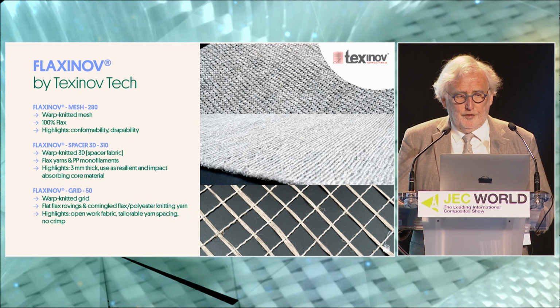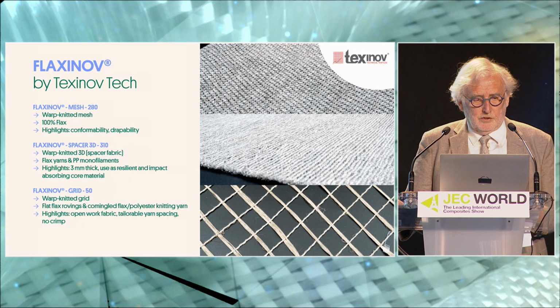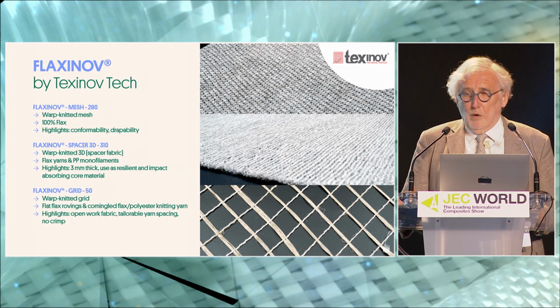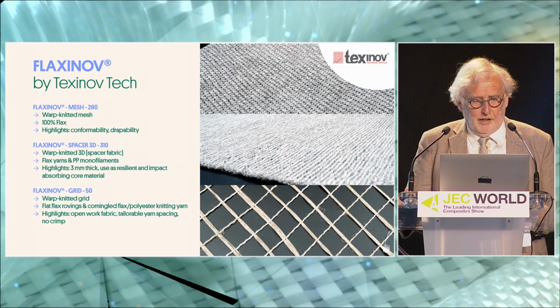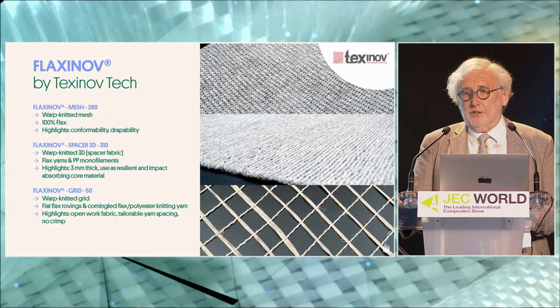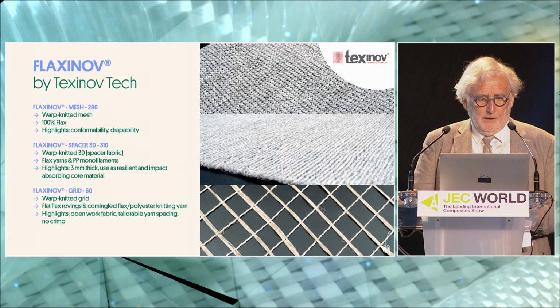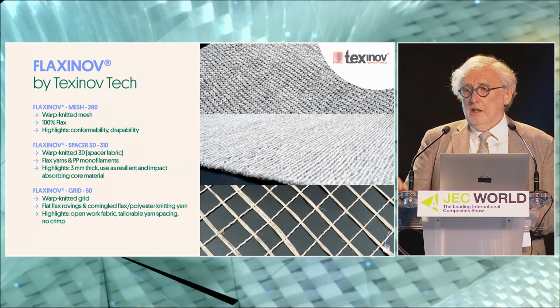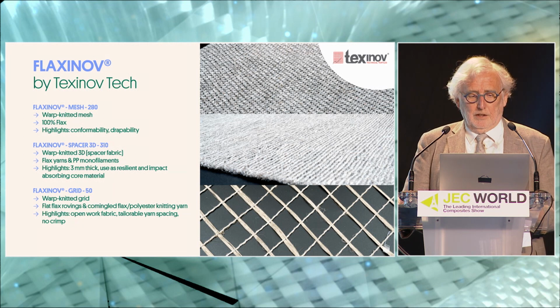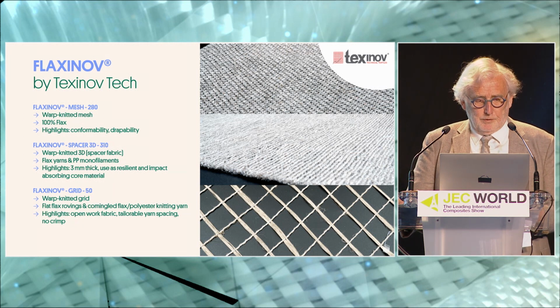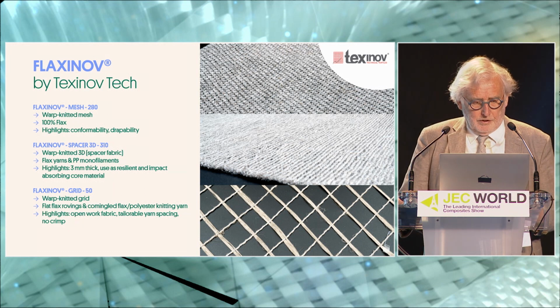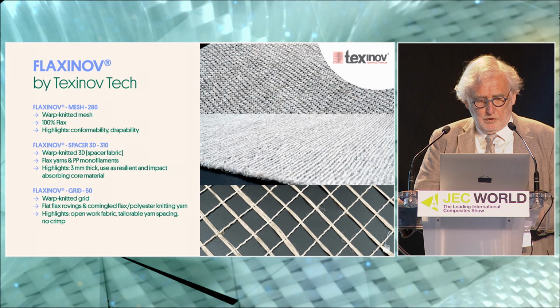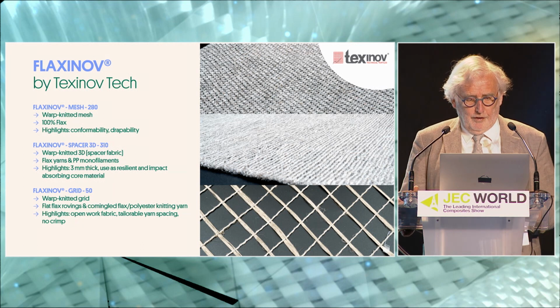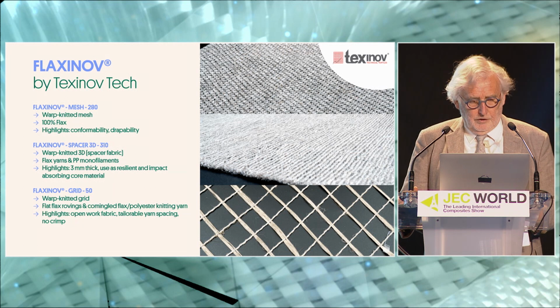Another is by Texinov, the Flaxinov range of materials. On the top you see a warp knitted mesh, which is 100% flax, which is very conformable. In the middle you see the spacer fabric, which is a 3D spacer fabric, which allows you to realize much thicker preforms and is excellent for impact absorption. And Flaxinov, which is a grid material and which can be used if you need an open work fabric. You can also tailor the yarn spacing, and it's moreover a non-crimp fabric.